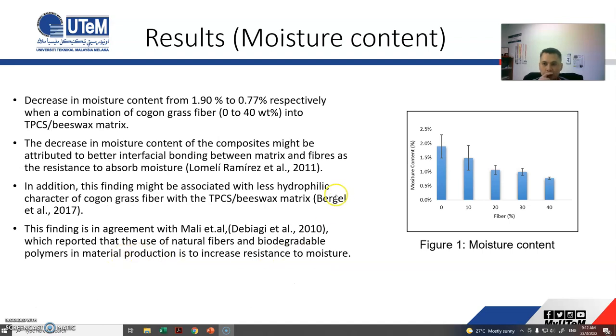Okay, so for the moisture content, as you see in the figure here, the moisture content tended to show a reducing trend as the amount of fiber increased from 0 to 40%. The decrease in moisture content of the composites might be attributed to better interfacial bonding between the matrix and the fiber, which resists moisture absorption. This can also be associated with the less hydrophilic character of Cogon grass fiber within the TPCS Beeswax matrix.